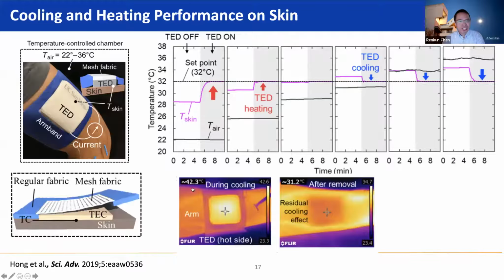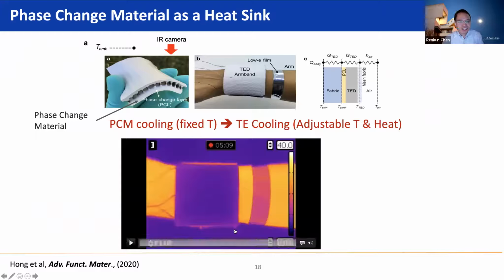And the other point I would like to mention is we show this in the concept of thermal camouflage, where you can show the skin is invisible or blank from the environment in terms of thermal signature. But the real idea is we can embed phase change material like wax particles into our elastomer to create a heat sink. And of course, we know the phase change material has a fixed melting point. As we mentioned earlier, for phase change material-based active cooling, it's difficult to control their temperature and heat flux. But we can utilize the thermoelectric to control the temperature and heat flux, but still use the phase change material as a heat sink. So you can essentially convert a fixed heat sink into an adjustable or tunable cooling device.